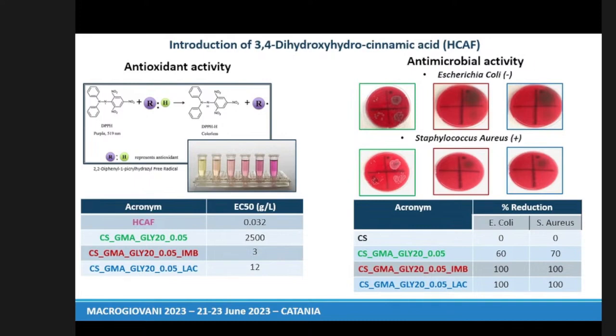And also in the evaluation of antimicrobial activity, we can see that with the introduction of antioxidant, we obtain a percent of reduction around 100%. These results are really preliminary, but they are really, really promising.